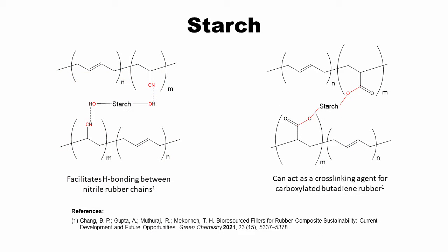Starch can facilitate hydrogen bonding between nitrile rubber chains, enhancing the rubber's strength and extension at the point of breaking. It acts as a particularly effective additive by providing the necessary donor groups for interchain hydrogen bonding to occur. In the case of carboxylated butadiene rubber, starch can act as a cross-linking agent, binding the rubber chains chemically through ester bonds. Since ester bonds are by nature covalent, they provide much more strength to the polymer chains than electrostatic interactions such as hydrogen bonding would.